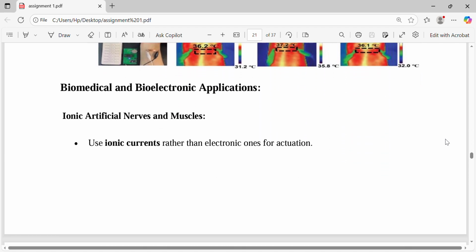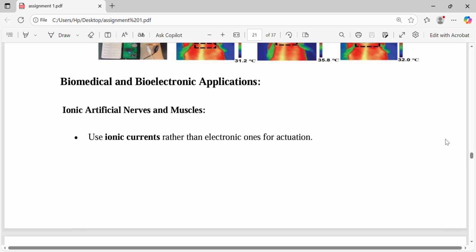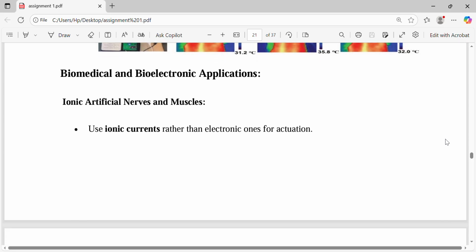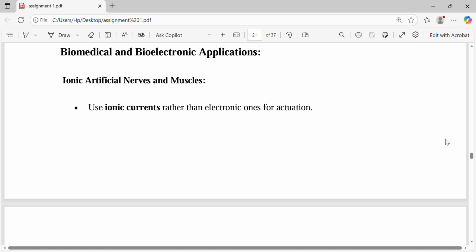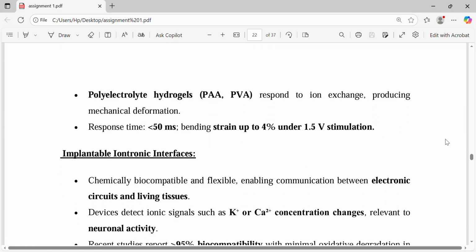Biomedical and bioelectronic applications. Ionic artificial nerves and muscles use ionic current rather than electronic current for actuation. Polyelectrolyte hydrogels respond to ion exchange, producing mechanical deformation. Response time is less than 50 milliseconds, with bending strain up to 4% under 1.5 volt stimulation.